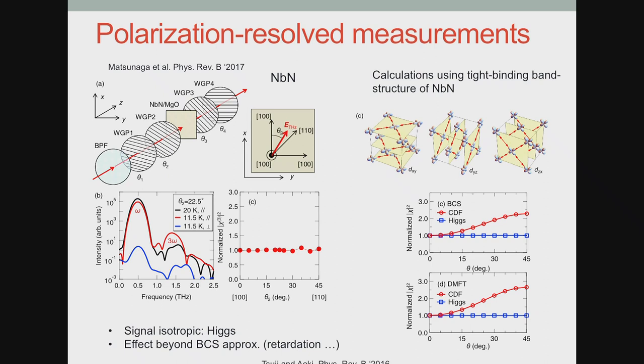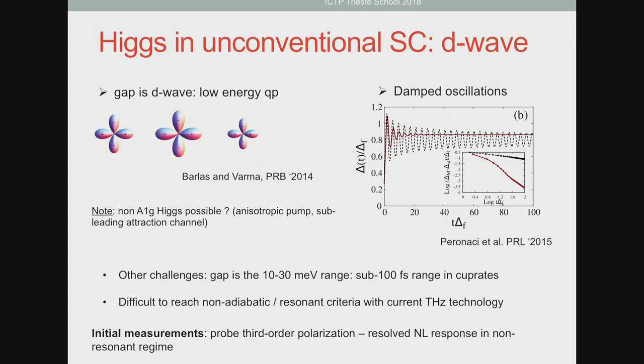There was some attempt to go beyond the BCS approximation by including retardation effects by coupling to some phonon mode. These calculations show that if you include retardation, you bring the contribution from the Higgs mode a bit closer to what you would expect from the pair-breaking mode. But I think right now this is still a bit speculative. Okay, so in the remaining part of this second lecture, let me now talk about some recent measurements we did in collaboration with the group of Ryo Shimano in Japan.